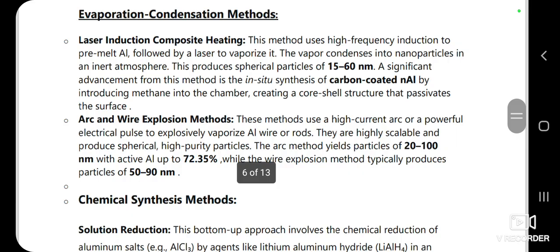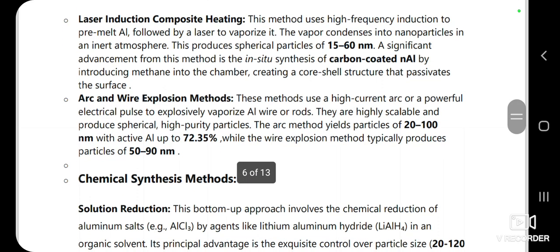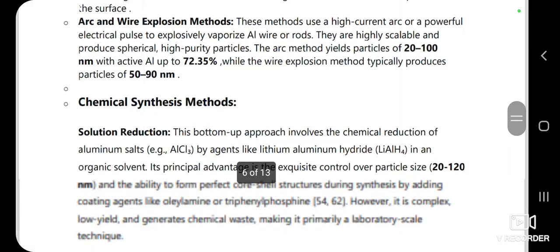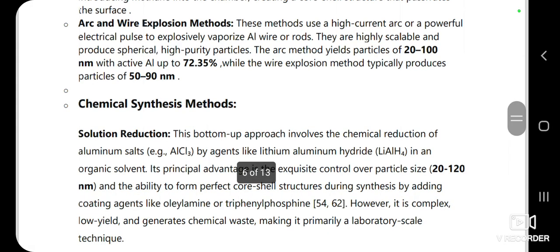Here we vaporize aluminium with a laser and let it condense into perfect spherical nanoparticles with 15 to 60 nanometers in size. We can even add methane to create a carbon coated nano aluminium by introducing methane into the chamber, creating a core shell structure that passivates the surface. And the next is arc and wire explosion methods.